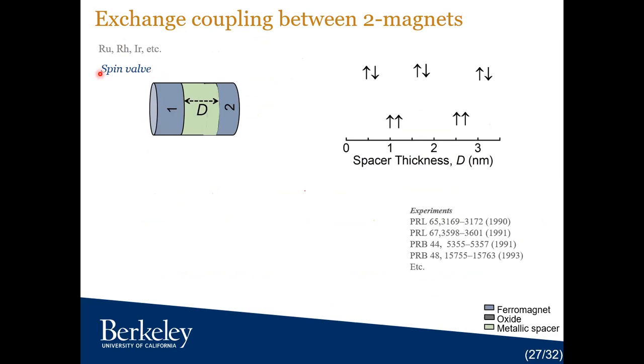It's observed in a spin valve. If you remember, a spin valve means two magnets separated by a thin metallic spacer. In the experiment that was done around the '90s, they increased this metallic spacer thickness, and at equilibrium these two magnets periodically switch from an anti-parallel state to a parallel state, to anti-parallel again, to parallel again. And that was quite amazing. It's happening at equilibrium, just by changing the thickness of the middle layer. And it's observed for transition metals, like when your metallic layer is ruthenium, rhodium, iridium, and there are other materials like copper. I haven't listed all of them.